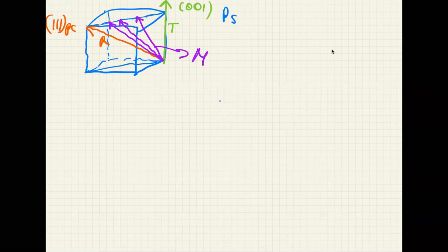that monoclinic phase is naturally related to rotation of the polarization. Okay, because to get from T to R, if you rotate the vector with an external field, you would immediately go into monoclinic phase. And since energies are equal here, that rotation through monoclinic phase has to be relatively easy. Okay.